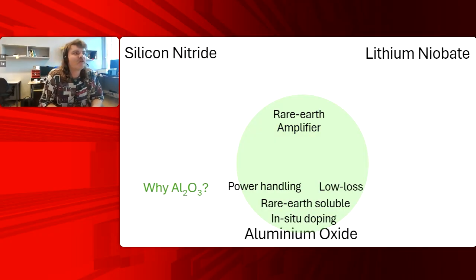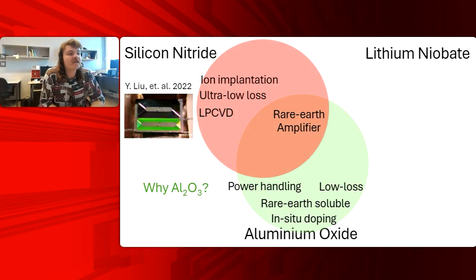You can have many different rare earth amplifying materials. As I mentioned already, the power handling in aluminum oxide, because it's linear, is an advantage. The material itself can be inherently low loss. It's very high rare earth soluble, and we can dope it in situ during the actual fabrication of the material. In comparison to silicon nitride, this relies on ion implantation after the fact, where high energy implanters are required, which you can see here in this very nice paper where they got very impressive amplification results in the Kippenberg group. Still relies on ion implantation, which is not done while the film itself is being deposited. I'll talk about that a little bit in the fabrication section of my talk. However, they can have very significant ultra low losses, and as I said, they are made with chemical vapor deposition.